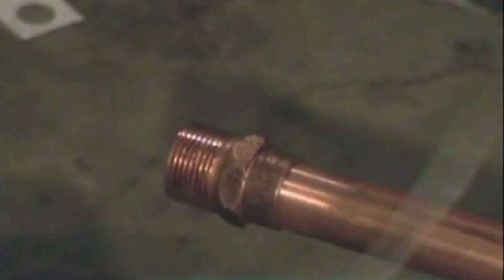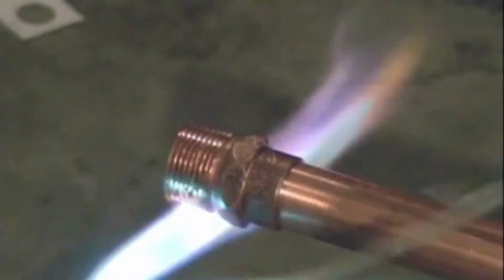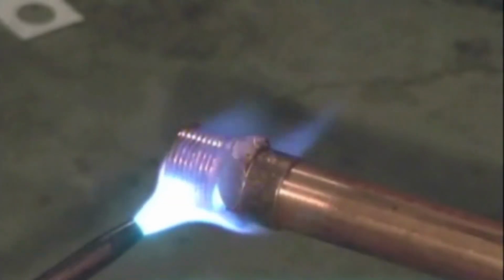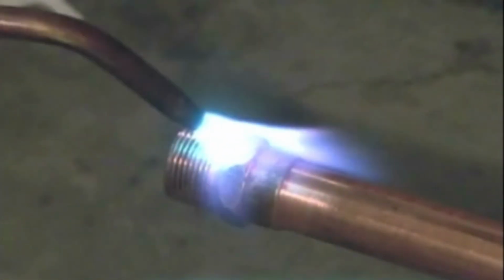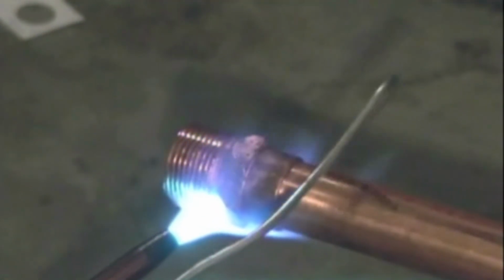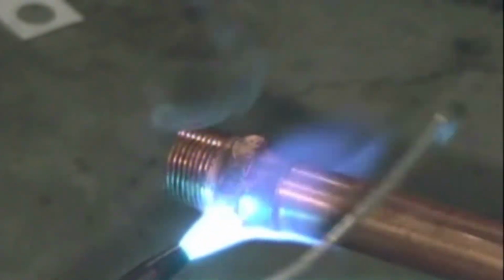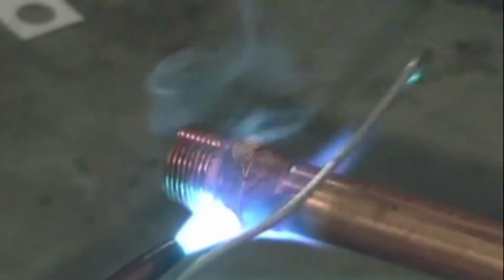Yes, the teardown. Before the torch is even ignited, the operator must completely disassemble the dielectric union, carefully remove the delicate plastic insert and the rubber washer, and set them far away on the workbench. You essentially have to gut the fitting to protect it from your own process. It's like performing surgery. It is. You isolate the bare brass piece, apply the flux, fit the copper pipe, and execute the solder joint. You establish the watertight bond while the fitting is entirely empty. And then comes the discipline of patience, because brass has a massive thermal mass. Brass retains heat exponentially longer than thin-walled copper.